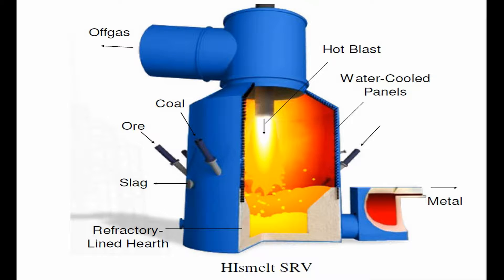The resulting process gas typically has a post-combustion degree of 50–60%. The key to the HIsmelt process is achieving heat transfer between the upper oxidizing region and the lower reducing region in such a way that the oxygen potential gradient is maintained. This is achieved via large amounts of liquid splash moving between regions, carrying heat with them. A certain percentage of this heat goes to water panels and lances, and the balance is used for smelting.